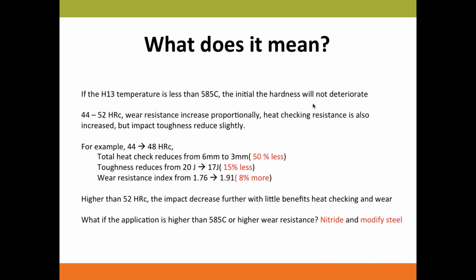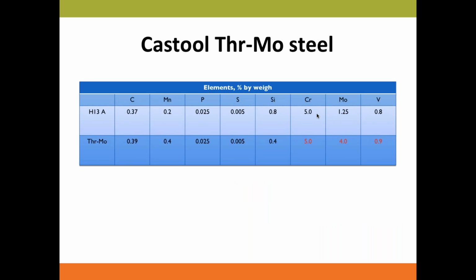So what if we need the steels to withstand or hold up to higher than 585? What we can do is we can nitride the steel, or we can modify the steel composition. As we know, when you increase molybdenum or chromium, the Rockwell hardness is going to increase as well. So in Castool, we tweak the composition in H13. We increase the molybdenum from 1.3 to 4% because molybdenum gives better strength or hardness.